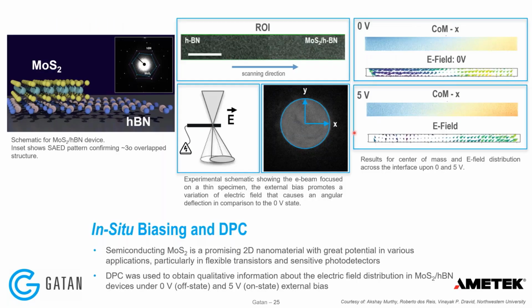Here is another example combining 4D STEM again with in situ biasing. This example is from Northwestern University using the K3 IS camera, looking at the interface of hexagonal boron nitride and molybdenum disulfide here. What they did is they collected 4D STEM data sets without biasing and with biasing the sample, and measured how the electric field at the interface of these two layers changes.